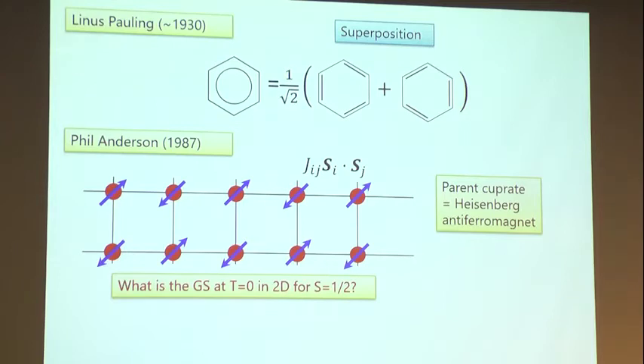But the conceptual question that Phil Anderson asked at the time was, if we distill this into the essence of just a 2-dimensional system without any interaction between the layers, and cool down to 0 temperature, then what is the actual ground state of this square lattice Heisenberg antiferromagnet for spin half? Of course, in the classical picture, we know that this is a Néel order like this, shown here. And that also applies to S equal 1 or S equal 3 halves and so on. But at the time, it was not known what the ground state of this is for S equal 1 half, which is the case of the largest, strongest quantum fluctuation.